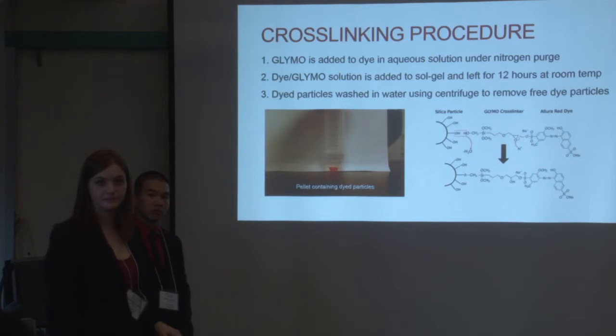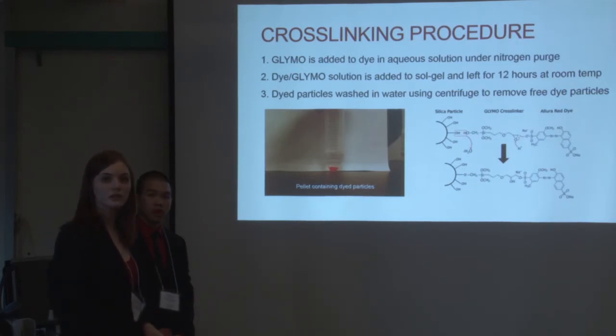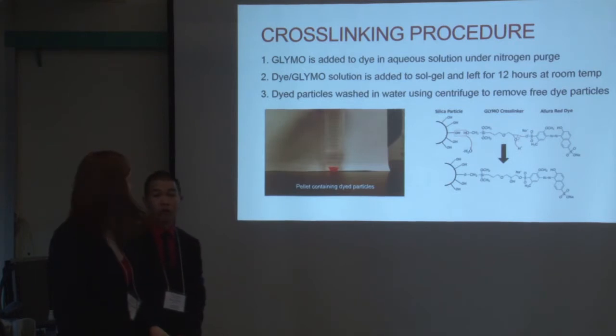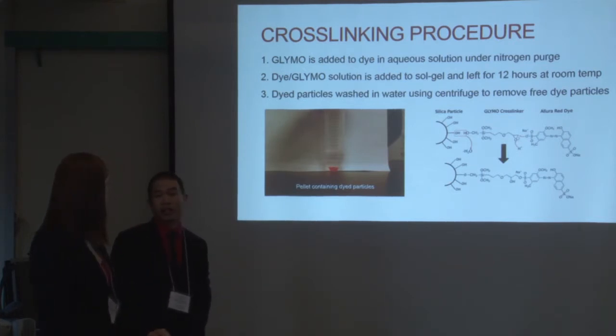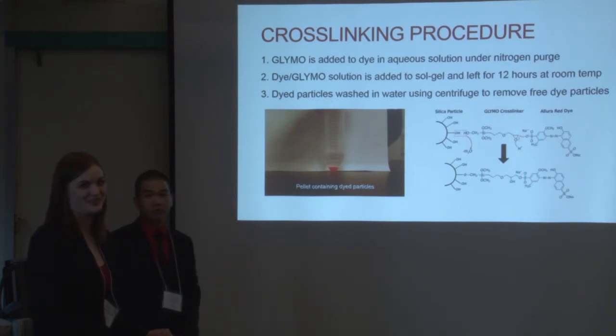How did you wash? Did you put it like a cake and put water through? Yep. And then we would centrifuge it and take off the... Is the dye soluble in water? Yes. So if the dye would leach out, you would be able to see. It's basically the color of Kool-Aid. In our first tests, we had no dye attachment when we tried physical absorption. Once we washed the particles enough times, it would just be a white powder again. But this way we were actually able to get the dye to be permanently attached.